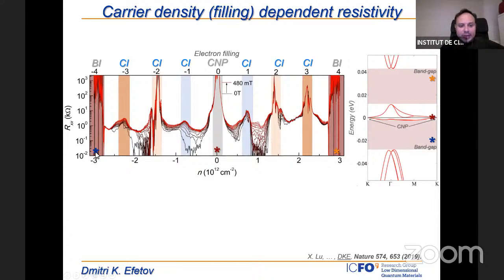The vice versa happens if we completely fill the entire band. On the other side, at positive charging of the full moiré bands, we also observe a band gap. Then in the center here, we observe a Dirac point. This is basically the point where those two gaps touch. All these features are explained by the single particle band structure, so we can look at this band structure and explain them. Except, as you can see, there's much more going on. There are now many more resistance peaks here. We observe resistance peaks here, here, and there, and also the same on the hole side.